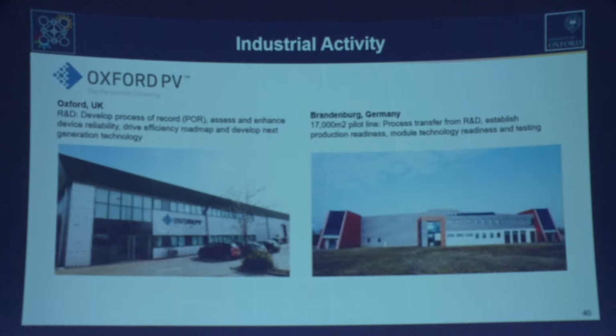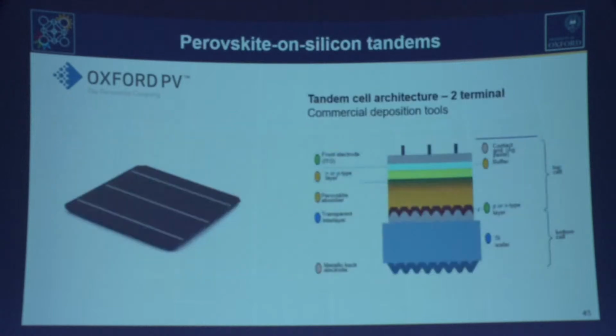So we take the innovations from the university group or that are occurring in the academic literature and test them to see whether they're efficient and stable and whether they can be employed in a manufacturing environment. Materials and systems that pass the tests and look like they make a real improvement to the core product baseline can then get transferred over into our site in Brandenburg. This is where we have been running a pilot line since 2017 and have just ramped up a production line, which is going to be the first relatively small scale, up to 100 megawatt production line for these perovskite on silicon tandems.